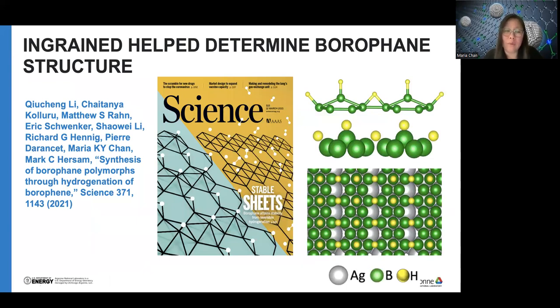So that was a very nice example, and it was fortunate that Mark Hersam needed the answer to that question, and we needed a tool that answers that question, because the animation I was showing you was a structure of hydrogenated boron, or borophane. Borophene is single layer boron, which is very different from graphene and silicene and others, because it's metallic, and boron really doesn't necessarily prefer a 2D structure. But anyway, Mark was able to hydrogenate it in the first step towards trying to isolate it electronically, and maybe induce a gap at some point. But the structure was not very clear, especially from STM alone.